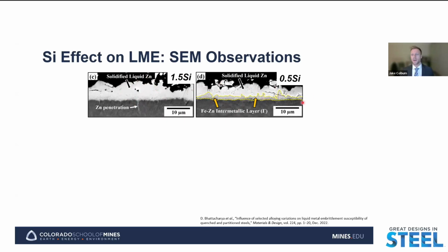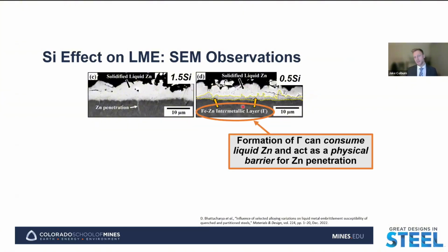And that's what we see here on the right with our low silicon containing steel, where at the interface we see the presence of this iron zinc intermetallic layer, specifically the gamma phase. And this gamma phase is important because its formation can consume the liquid zinc that is present, as well as act as a physical barrier to further zinc penetration. So at elevated temperatures, at our test temperature, if this continuous physical layer of the gamma is present and we have liquid zinc above, that's going to create a barrier to the liquid zinc further penetrating the substrate,